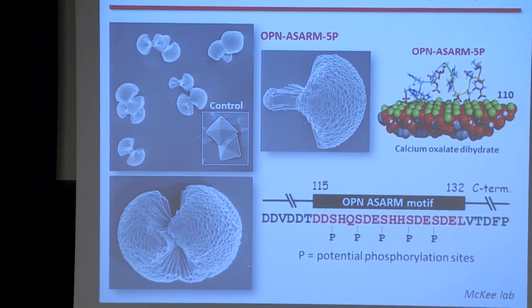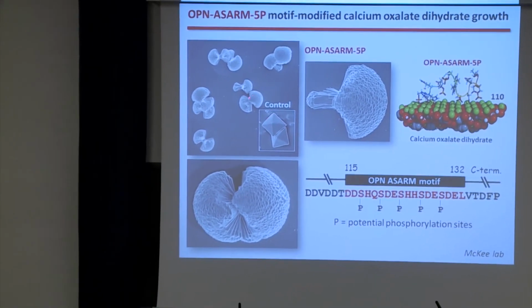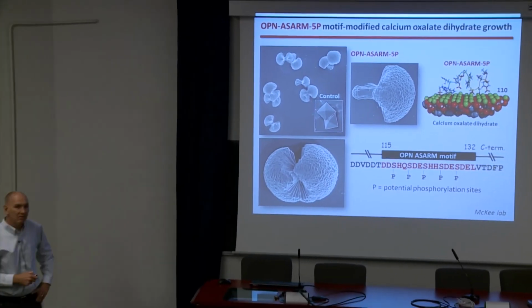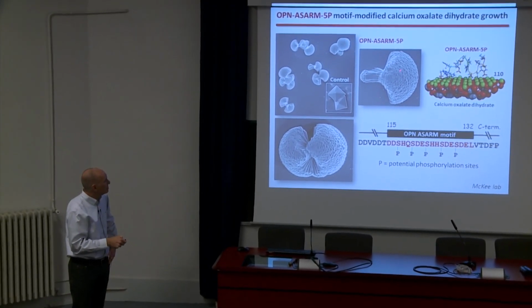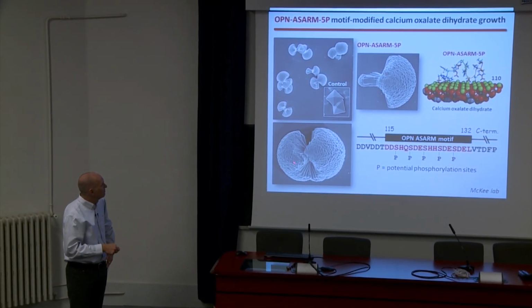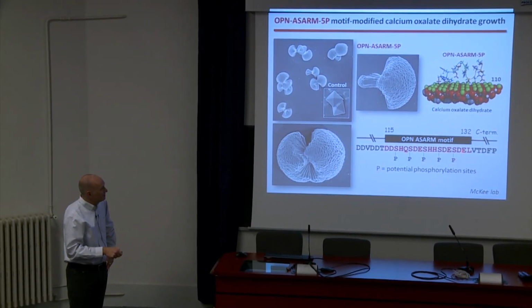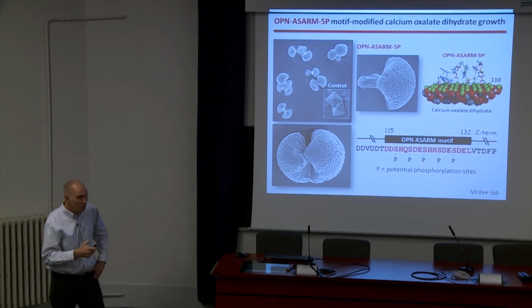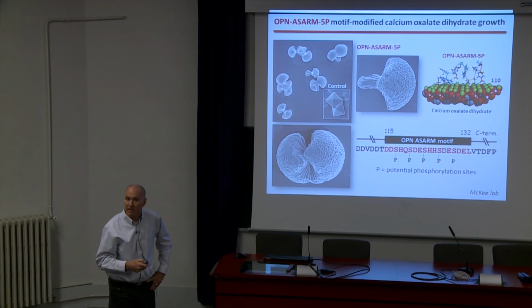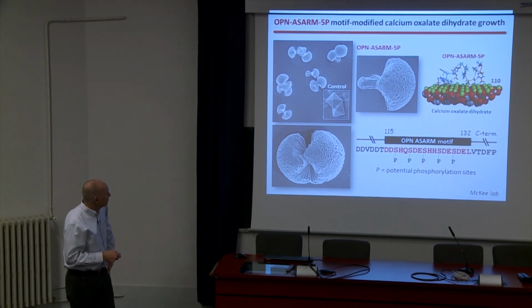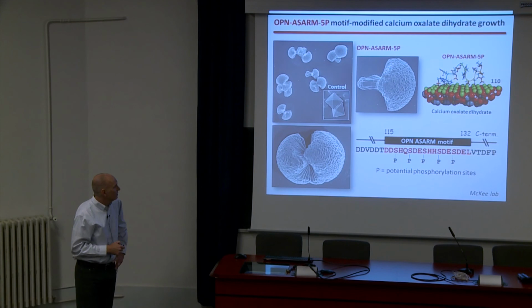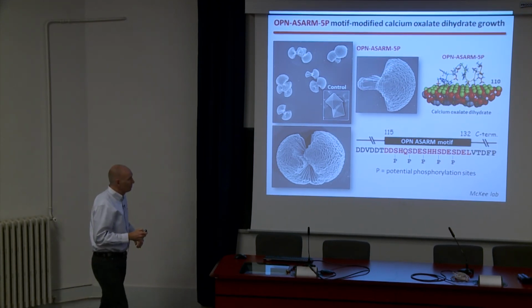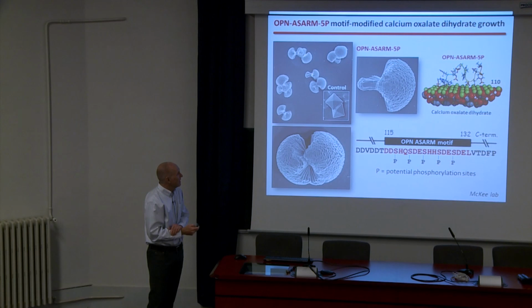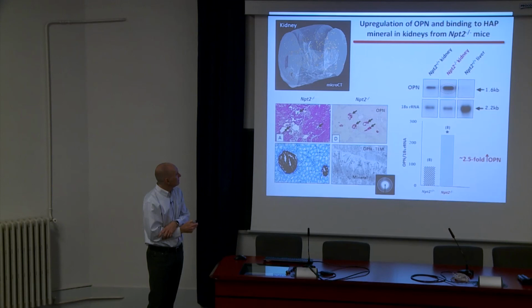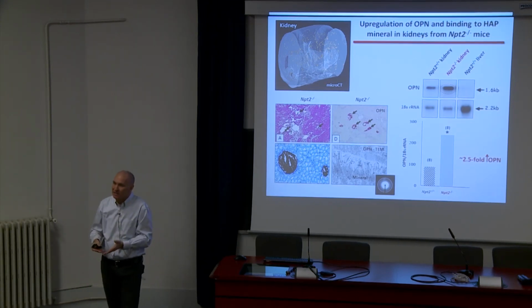We could remarkably go from a normal crystal to something very similar to what we saw in vivo, dumbbell-shaped crystals, lots of calcium oxalates. They extended and grew in various ways, and this is now with a completely different peptide motif. So the two peptide motifs do things a little bit differently to these calcium oxalate crystals. But it's remarkable how they actually reproduce that dumbbell. I don't know if it's a twinning kind of growth or what. We're preparing a paper on that now, and I can speak to Dr. Garcia Ruiz about that. All right, and then the calcium phosphate kidney stone model.